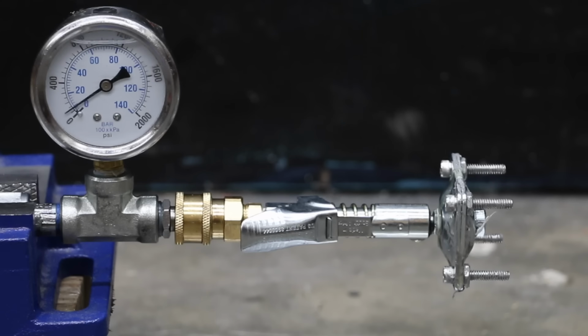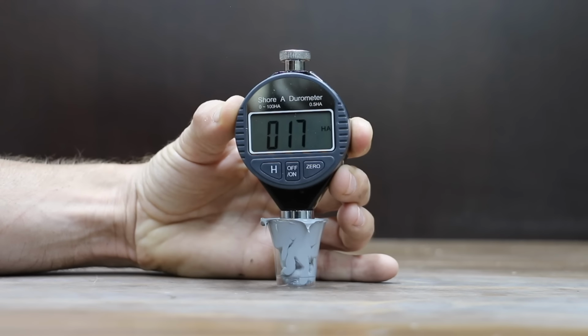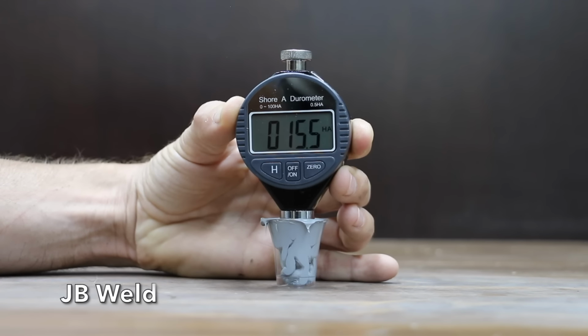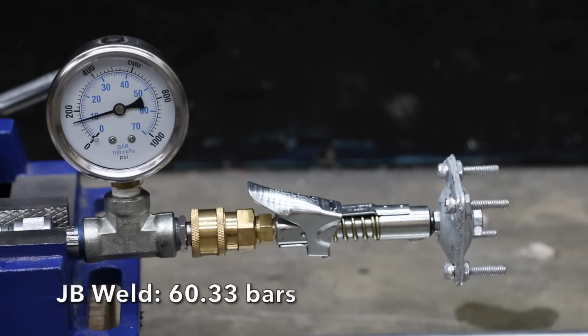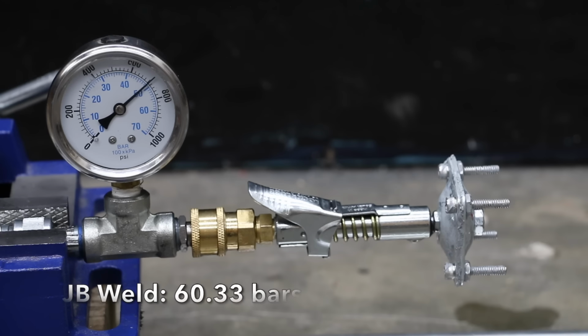I went ahead and swapped out the 2000 psi gauge for a 1000 just to make it easier to get a precise measurement. And the JB Weld is also a great RTV, but it's not as hard at only 15.5 compared to 35.5 for the Permatex. And the JB Weld made it all the way to 875 psi before blowing off some pressure.